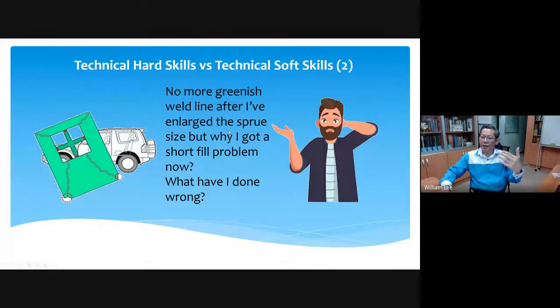But at the same time, after he enlarged the sprue, combined with the high melt heat, he experienced nozzle leaking. Then he experienced a short shot problem when he lowered the melt heat. When you lower the melt heat, it means you do not have enough heat, and then you have short molding. Instead of solving the old problem, now you create a new problem. So the weld line may be solved, but because you lowered the melt heat and enlarged the sprue size, you end up with the short shot problem. You therefore have to understand the science behind this process. How do you tackle the problem by looking into the inside of this molding process?